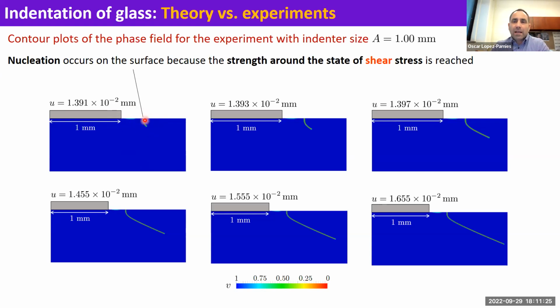And the reason is that nucleation is controlled here by the shear stress, the shear strength rather, of the glass, right? That is what actually is being exceeded, and that is what triggers nucleation. It's not tensile strength, as many people believe. It's actually shear strength that controls nucleation. Once you have nucleation, up you go, you have propagation a la Griffith.